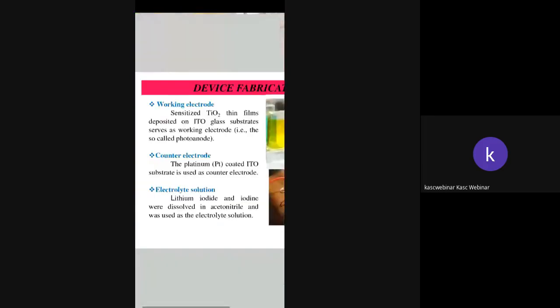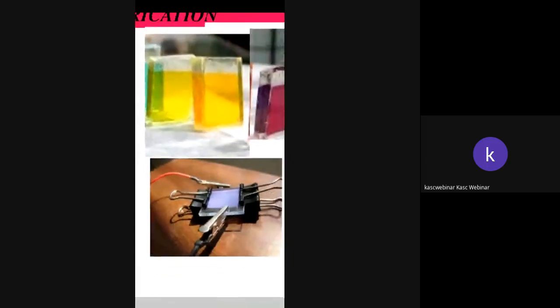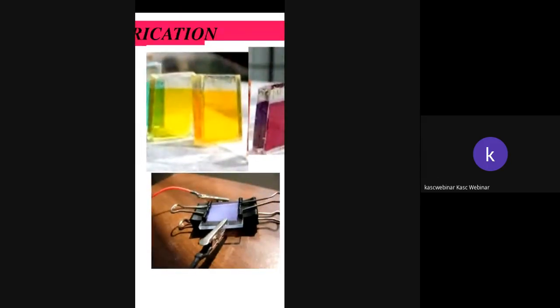We have collected beetroot essence and we have coated it over titanium dioxide thin films, and we have studied the photo response. And this figure, the third one, shows how we have fabricated the solar cell at laboratory level. The photoanode and the counter electrode are brought into contact, and in between the electrolyte solution is dropped so that we can construct a solar cell.